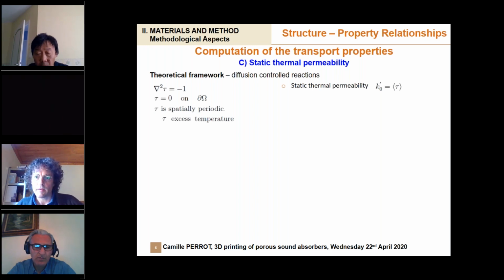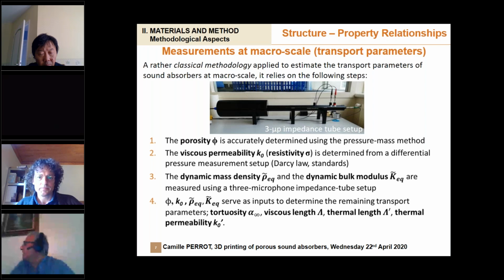All these parameters are included into the Johnson, Champoux, Allard, Lafarge model. And you have some simpler models, let's say Johnson, Champoux, Allard. You can get some connections between these transport parameters, which are carrying physics, and some other macroscopic or semi-phenomenological parameters. This is not the only way to describe physics, but this is an interesting way because you deal with macroscopic or transport parameters which are carrying physics, and you can measure these parameters from direct and acoustical measurement techniques. Here is a way to measure these transport parameters or macroscopic parameters.